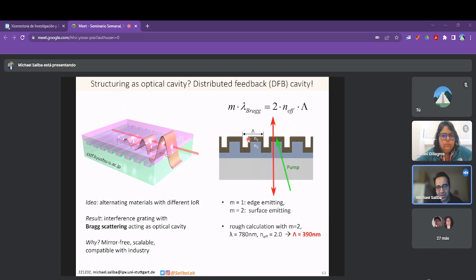And you see here the basic thinking behind it. This is the Bragg condition for orthogonal pumping when the sine is 90 degrees or pi half. And you see here, if we use m equals 2, this is a second order surface emitting mode. It's a bit difficult to do an edge emitting mode. We have the periodicity here, lambda, and then we need to have an effective index of refraction. See that here? And doing a back of the envelope calculation with the perovskites we could do at the time at 780 nanometers and an effective refractive index of 2, so it's just a geometrical average, the corrugation of the structure needs to be about 400 nanometers, 390.